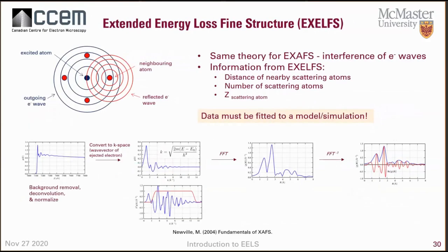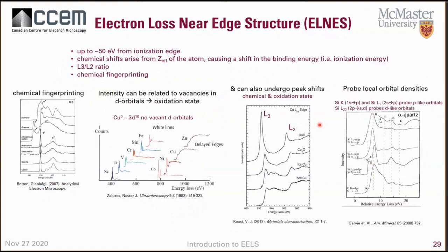The extended energy loss fine structure (EXELFS) probes nearby atoms and is very similar to the extended fine structure of X-ray absorption spectra — interpreted the same way. It can give you information about the distance to nearby scattering atoms, number of scattering atoms, and identification of nearby atoms. However, it's a very intensive technique requiring fitting your data to a model to get meaningful information. Normally, we just focus on ELNES and regular ionization edges.